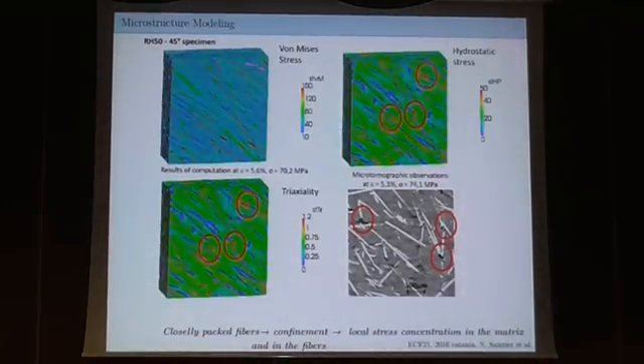So we did microstructure modeling with periodic microstructures, FFT computations, and we clearly see that in areas where you have compact, fully packed fibers, you have high hydrostatic stresses, you have high principal stresses, you have deviatoric part also. So these stresses and stress distribution promote all those damage parameters, and what we want to do next is try to relate these kinetics to these local fields in the microstructures.